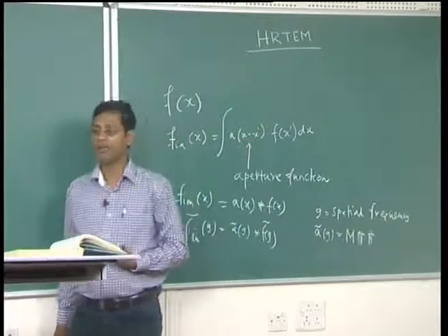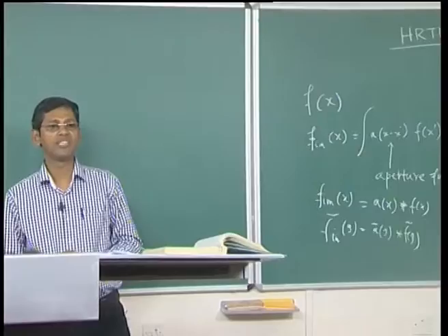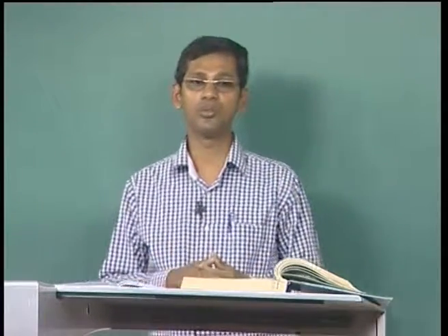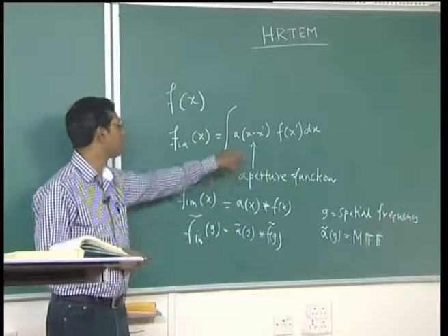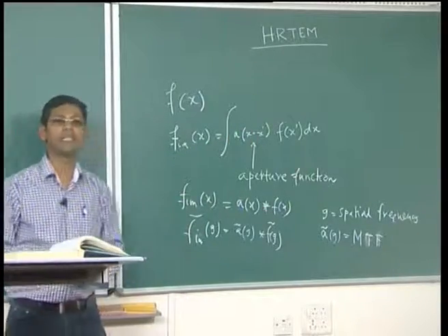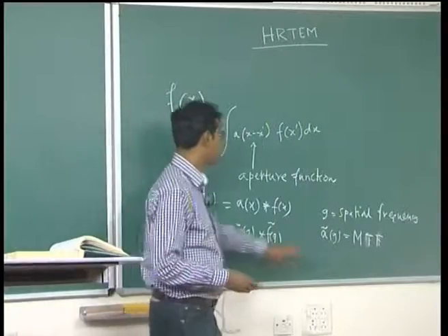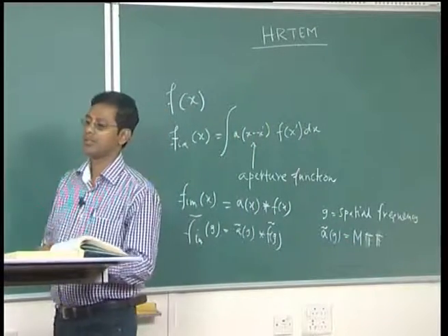So, in any simple camera, even though we assume that whatever is there in the object is getting directly projected into the image plane, that is not true. This is what actually dictates many things, like the resolution of the imaging instruments, the information level of the imaging instruments and many other aspects. So every imaging device is characterized by this function called the modulation transfer function, or simply the transfer function in the books.